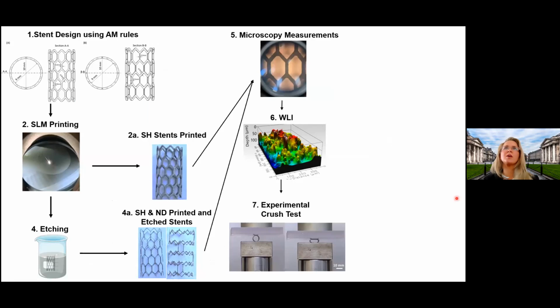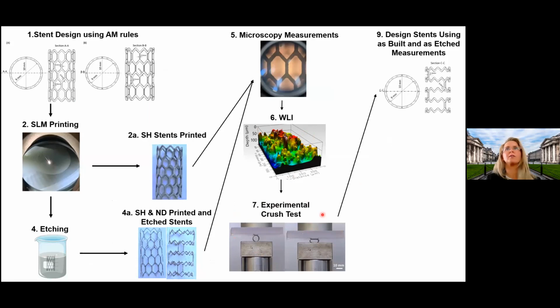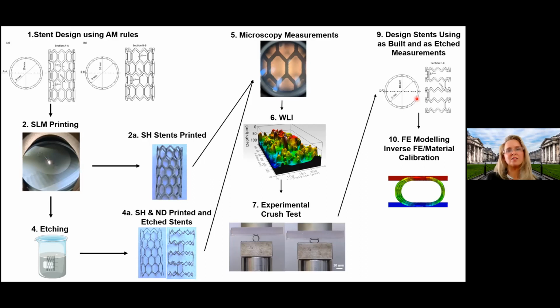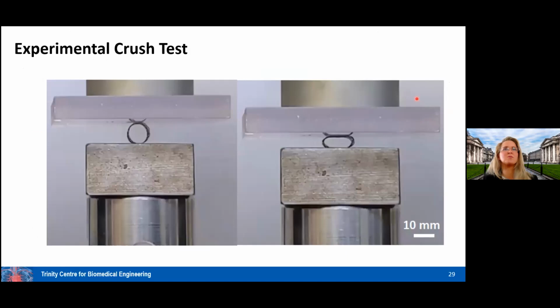So the next stage is once we had our white light interferometry, we'd reduced our surface roughness. We now wanted to see, well, would these stents have the appropriate radial stiffness to implant and perform a coarctation, so open up a vessel and keep it open. And then we also wanted to see how did that compare for the as-built and those that were etched. Then we're going to create that FE model, as I'll show you, to do this inverse FE to work out what is the stiffness of the titanium that we use when it's printed. And then I will show you the patient-specific models.